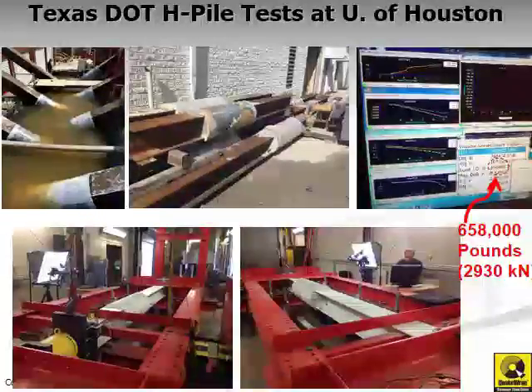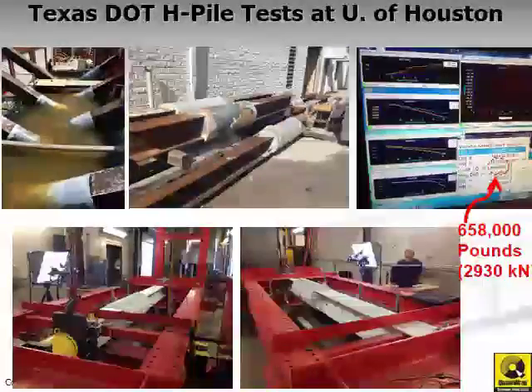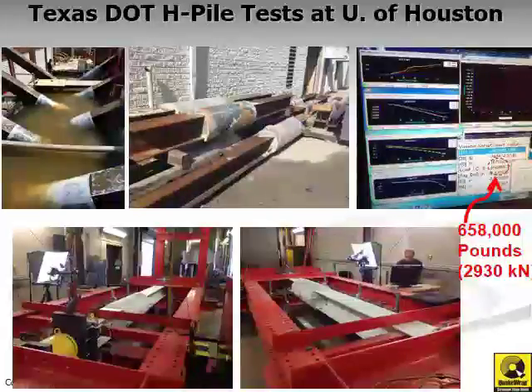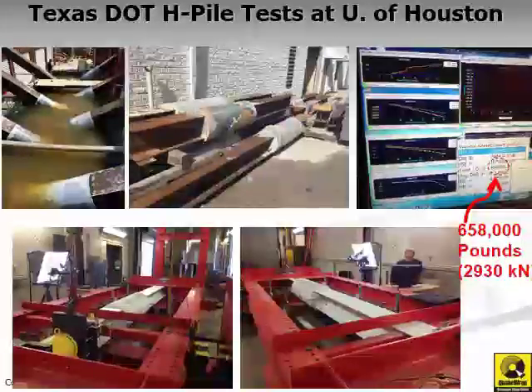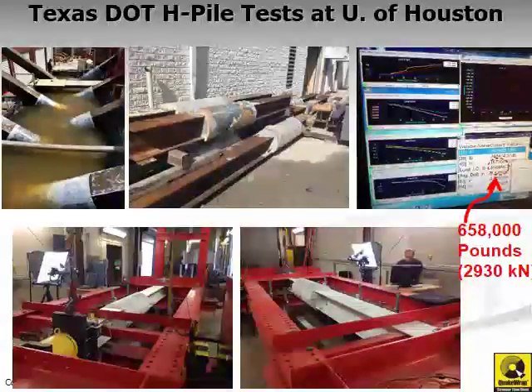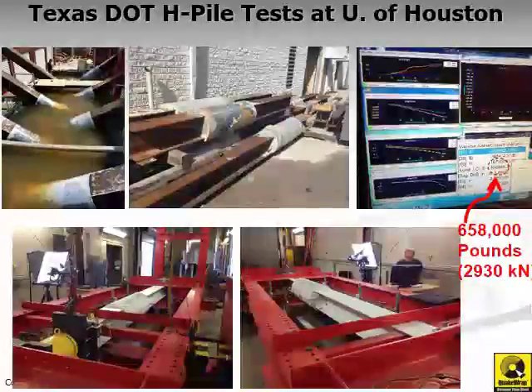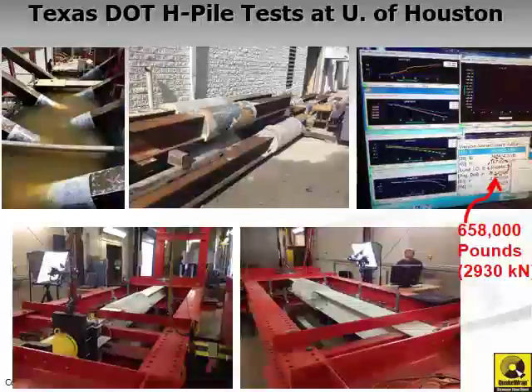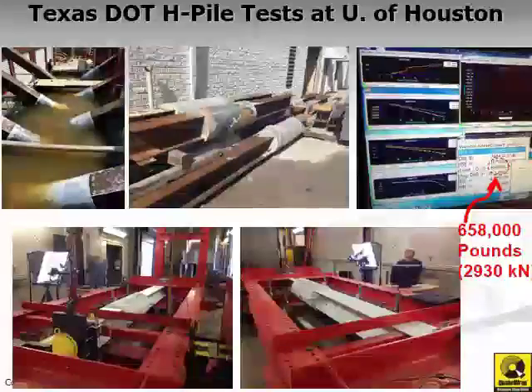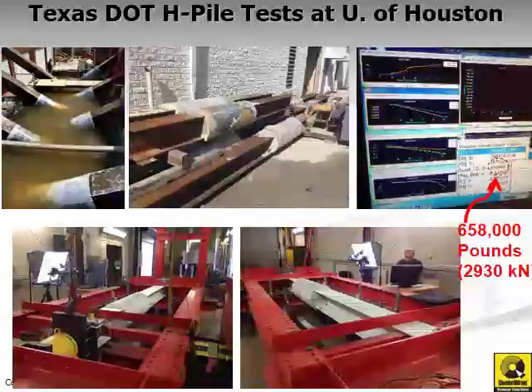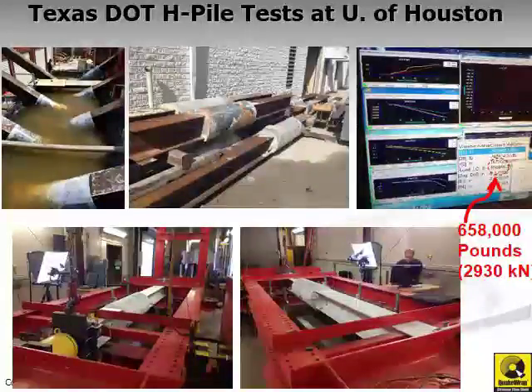Here is again a view of the specimens after they had been repaired and sitting outside of the laboratory at University of Houston. In the red frame, it shows one of the specimens being tested under axial load. As you can see in this particular case, the column took around 658,000 pounds of load before the test was stopped.